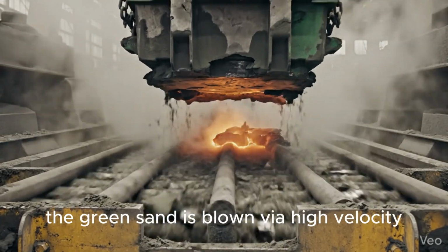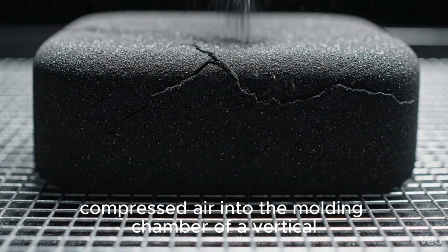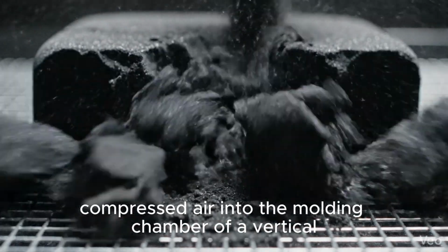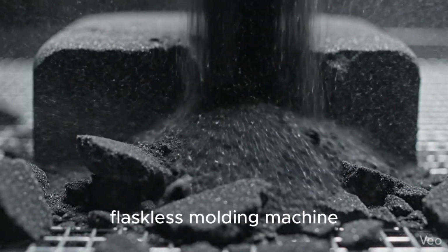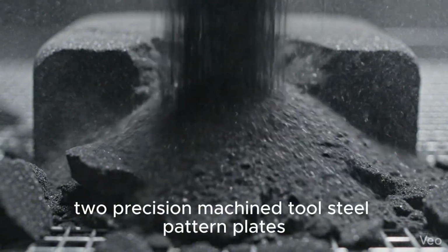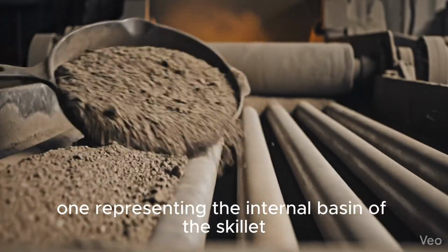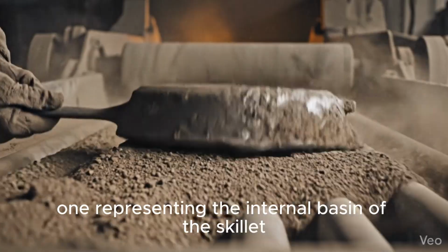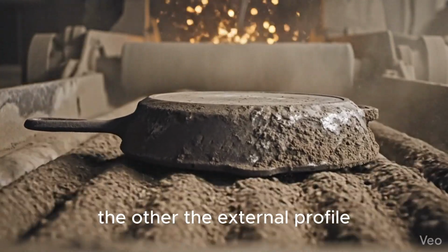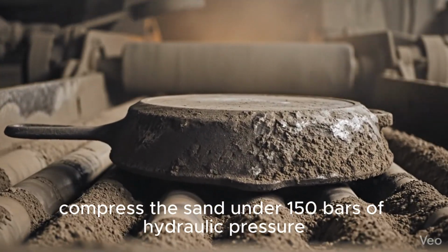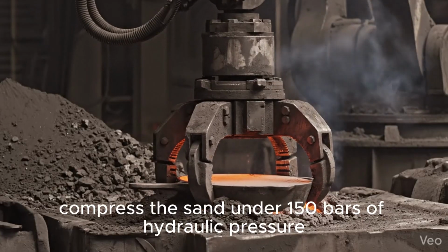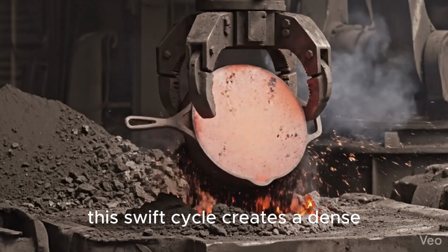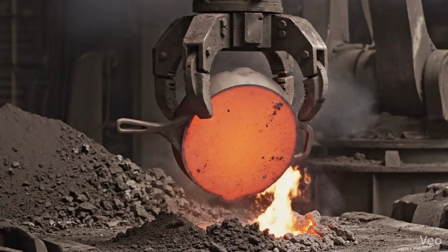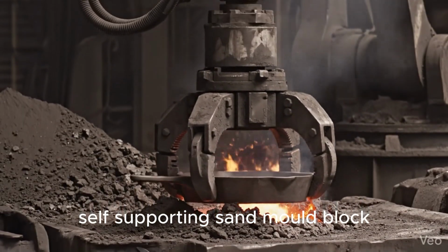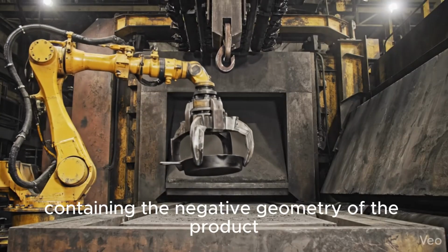The green sand is blown via high-velocity compressed air into the molding chamber of a vertical flaskless molding machine. Two precision machined tool steel pattern plates, one representing the internal basin of the skillet, the other the external profile, compress the sand under 150 bars of hydraulic pressure. This swift cycle creates a dense, self-supporting sand mold block containing the negative geometry of the product.